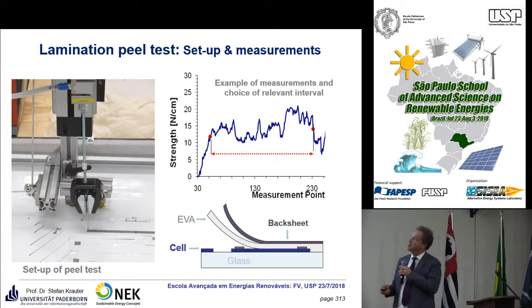This I was mentioning, this was the peel test here. You cut the module here and you peel it off and you measure the force here, in Newton per centimeter, and this is an indicator of how good the lamination has been made.